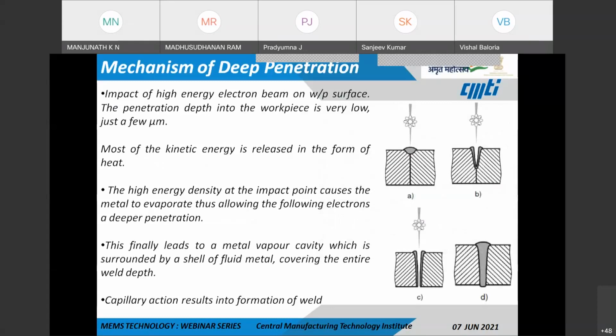So, mechanisms of this depth of penetration. With the high impact energy of these electron beams on the work surface, the penetration depth into the workpiece is very low, just a few microns, and most of the kinetic energy is converted into heat. The high energy density at the impact point causes the metal to evaporate, thus allowing the following electrons to go deeper. So once these electrons hit at first, they only transfer heat energy and the metal starts to vaporize, allowing the incoming electrons to pass through the molten weld pool. And this finally leads to a metal vapor cavity, which is surrounded by a shell of fluid metal covering the entire weld depth.